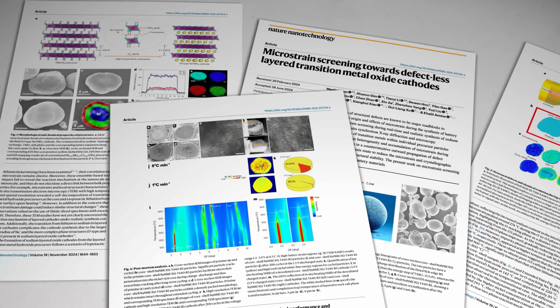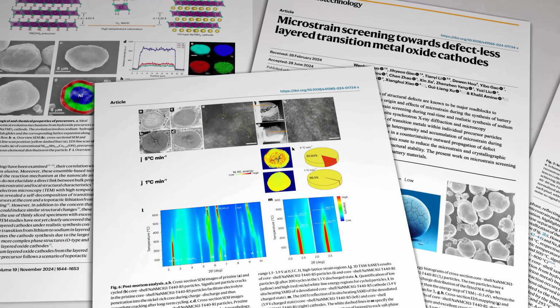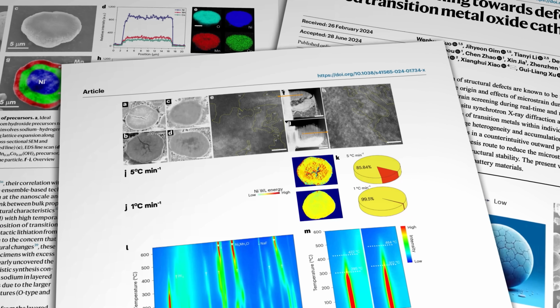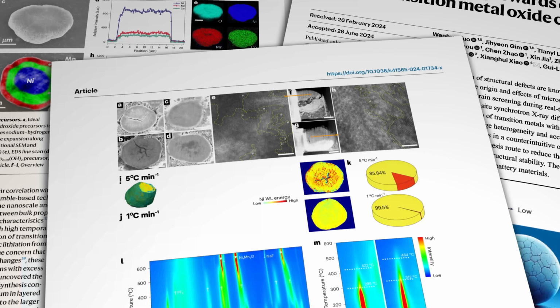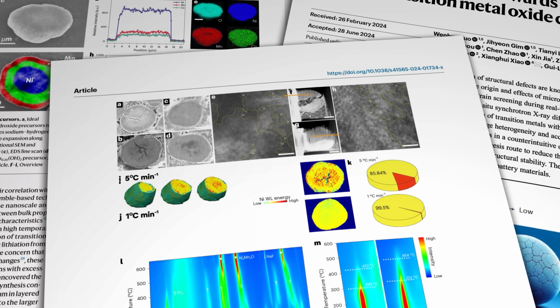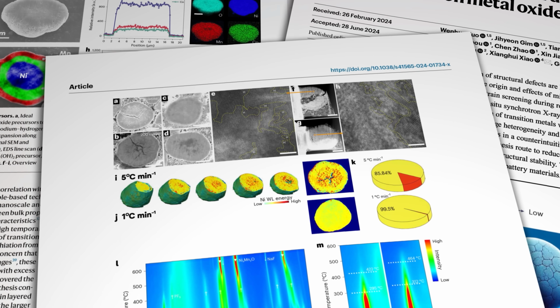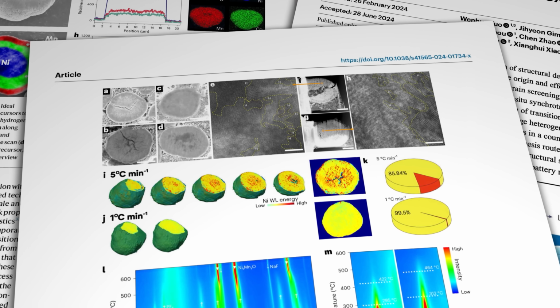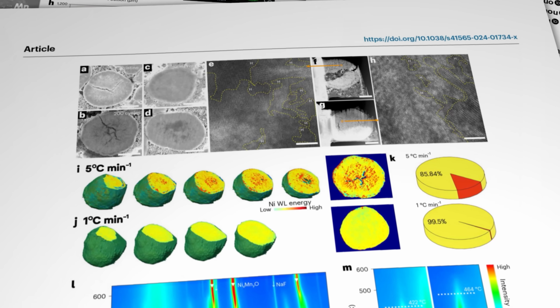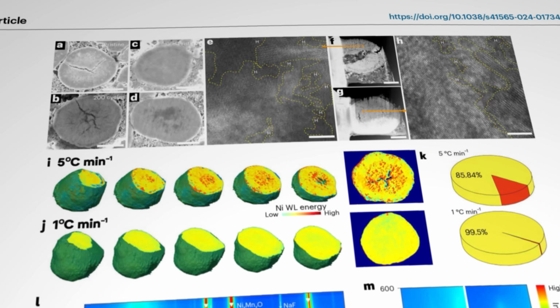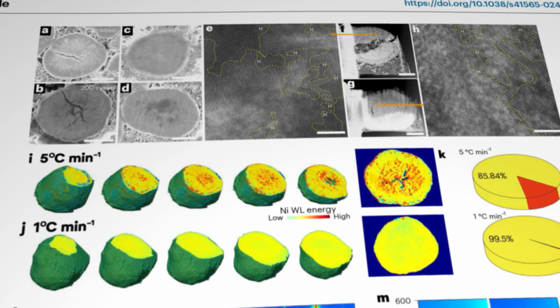But it turned out there was another variable at play too, and that was the rate of heating during the manufacturing process. The test rig was run twice with both cathode material configurations and with exactly the same start and end temperatures. The first run was heated at a rate of 5 degrees Celsius per minute, and the second was heated at a rate of only 1 degree Celsius per minute. While the faster heating sample showed particle cracking, no such problem appeared to be occurring with the more slowly heated samples.